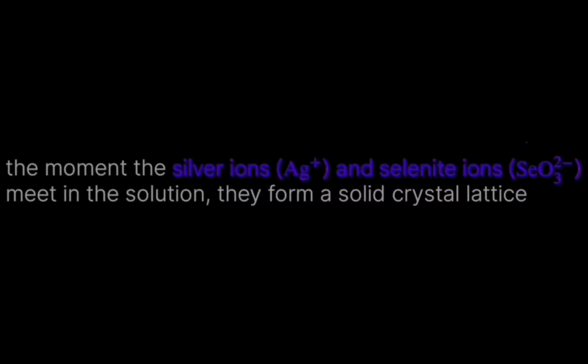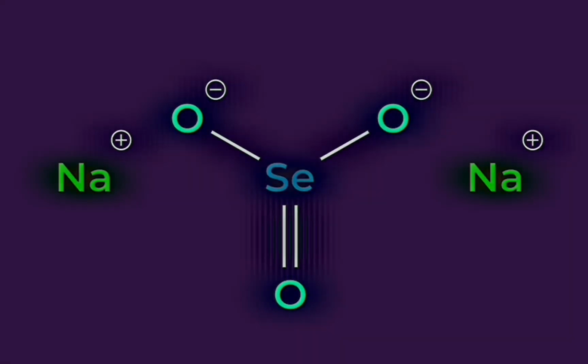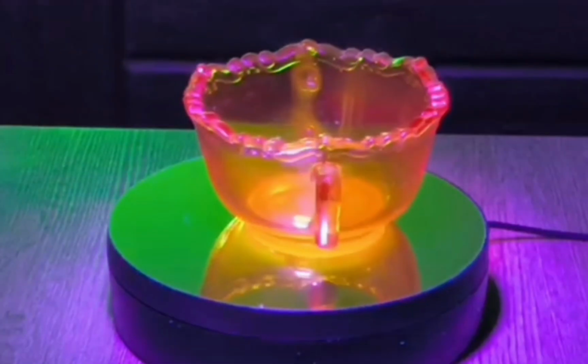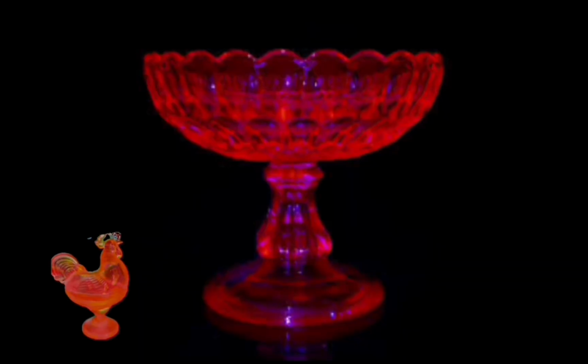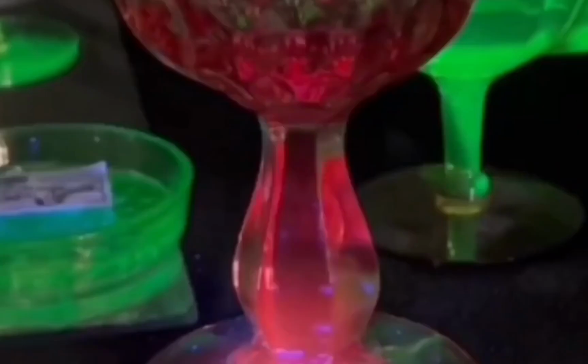Sodium selenite is used to decolorize glass, neutralizing the green tint from iron impurity. In larger amounts, it turns glass various shades of pink or ruby red. Selenium dioxide is too volatile. You need time for the selenium to diffuse into the molten glass.